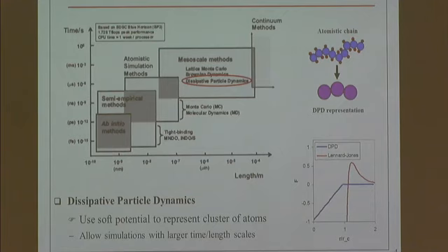So we reduce the number of molecules we need to model and track. And we also coarse-grain it in the way we replace the Lennard-Jones potential that we use in MD with a soft potential, which is essentially a linear potential, which is shown here. And this potential is soft, so the time step we can use is much larger than we would need to use in MD. Right. So these two things help us to drastically increase the system time we can model using this method.